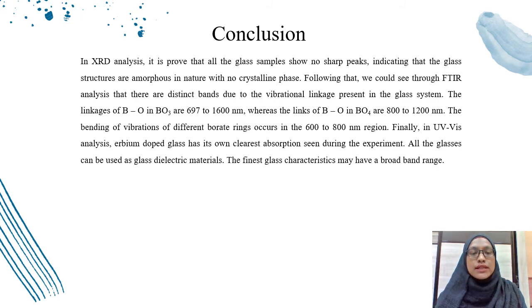Following that, the FTIR analysis shows distinct bands due to the vibrational linkages present in the glass system. The linkage of BO in BO3 is at 697 to 1600, where the links of BO in BO4 are 800 to 1200. The bending vibration of different borate rings occurs in the 600 to 800 region. Finally, in the UV-VIS analysis, erbium doped glass has its own clearest absorption seen during the experiment. All the glasses can be used as glass dielectric material. The finest glass characteristic may have a broad band range.